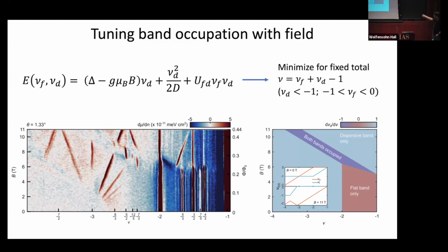where if you imagine sitting at 11 Tesla and increasing the number of holes in your system, well, in this purple strip, actually both bands, the flat and dispersive bands, are partially occupied. So as you're going up and up and up, you occupy first the dispersive bands. Then within the purple strip, you start to empty the dispersive bands and occupy the flat bands. And this strip corresponds exactly to where we see these charge-ordered states.